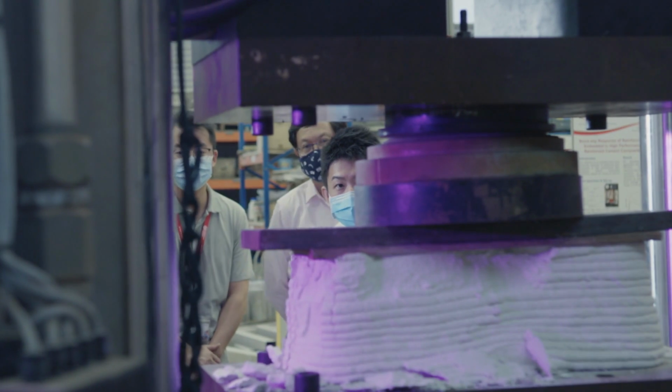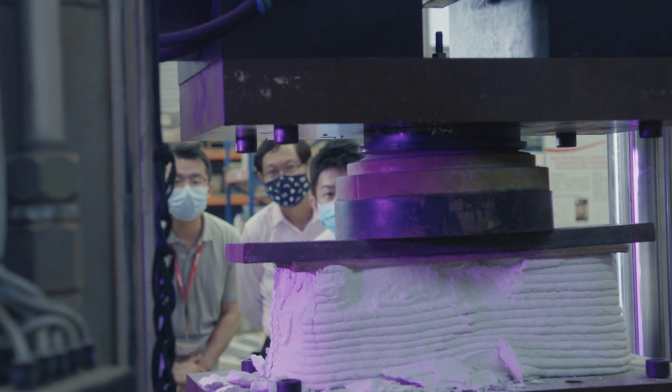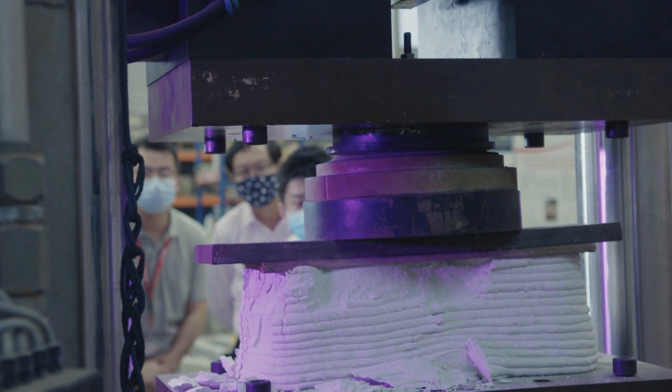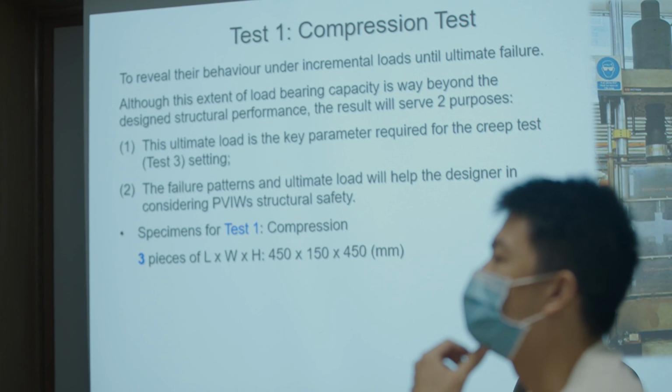We did a material test, and we want to understand material properties of the concrete printing structure. In terms of the 3D printed shells that we have just seen downstairs, you will find that there is no reinforcement between the layers of the 3D printed concrete. We need to improve the bonding between the cast-in concrete and the thick shell if we want to also utilize the outer shell as part of the dimensions for the concrete column. The resistance of the specimen we have tested is quite high, so I think 3D printed concrete walls is a very promising application of 3D printing concrete.